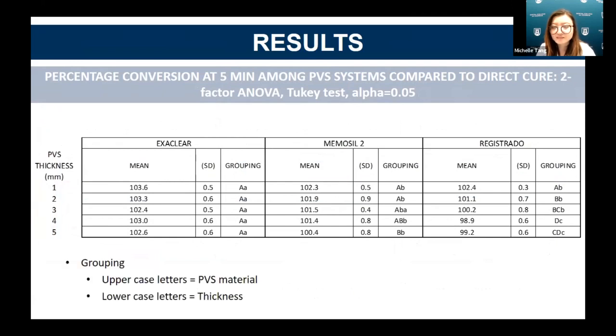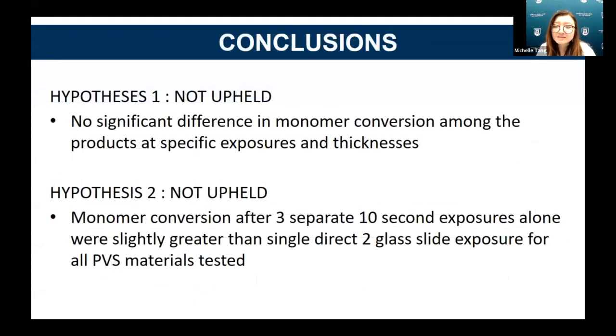5 groups were organized based on the results, in which the uppercase letters represented PVS materials and the lowercase letters represented the thickness. Specimens within the groups with similar letter identification were found to be not statistically significant, which leads us to the conclusions. At this time, there does not seem to be a significant difference in monomer conversion among product thicknesses, which indicates that our first hypothesis was not upheld.